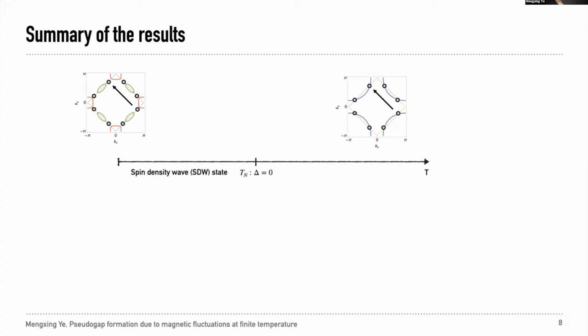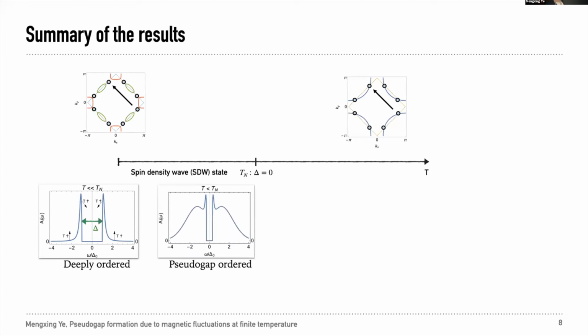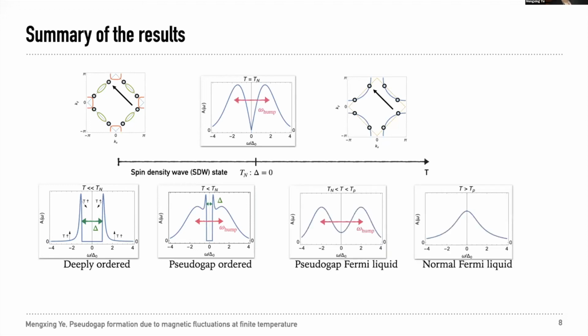Now let me go through the qualitative findings from our results by walking you through the evolution of the spectral function as temperature varies. At low temperature, deep in the SDW ordered state, the spectral function looks like the mean field picture, which is peaked at the finite energy determined by the SDW order parameter. As the temperature increases, the SDW peak shrinks, and in the meantime, another hump feature appears. As the temperature further increases above the Néel temperature, there is no SDW gap, but this hump feature remains all the way to a much higher temperature. Then the system recovers to the normal Fermi liquid-like behavior.